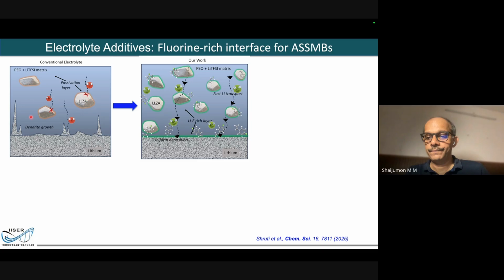And you have a problem here because you're using lithium and these kind of dendrites keep forming. And the moment these dendrites form, you have a dendrite at this end which pierces through and shorts the battery. So what we have done, one of my postdocs, Shruti, very cleverly came up with an interesting approach wherein a simple coating is given. In fact, we add some additives into this solid electrolyte called fluorine-rich additives. That decomposes and forms a thin layer all across. You can see that green layer schematically drawn here.